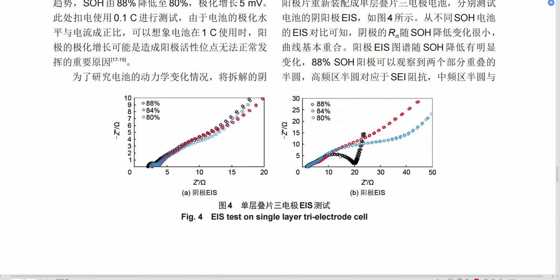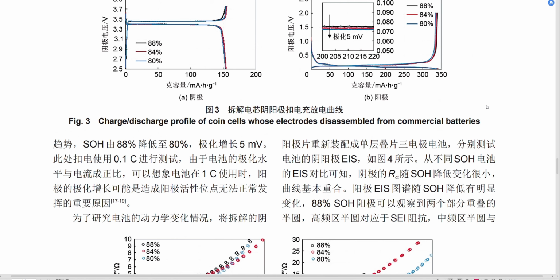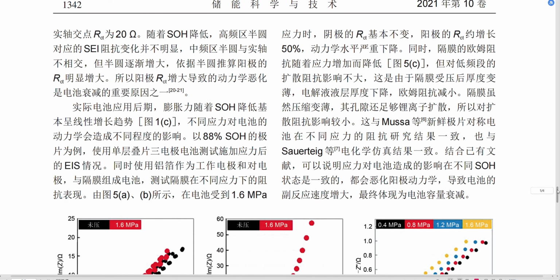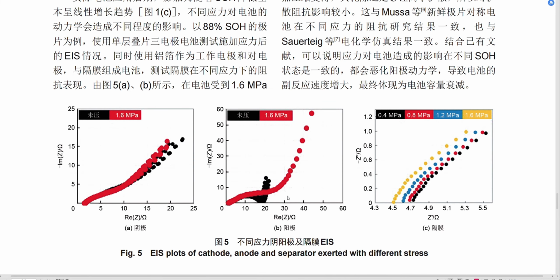So you'll firstly see the EIS shape changing from 88% onward in capacity retention, and then after 84% to 80% capacity fade, the charge transfer resistance also changes a lot. So which means in their data, the charge transfer resistance changes mostly in the anode side after capacity fading. So this is another supporting evidence for their claim.